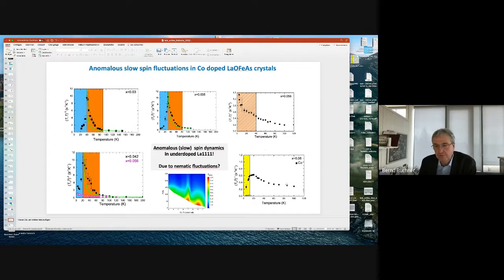Even if you go to the best superconductor, you still have this increase of the relaxation rate, telling you you have a very unusual slowing down of magnetic fluctuations. So magnetism is highly anomalous here in this sense. And of course, the natural way to explain this is, okay, we have these nematic fluctuations here in this region, and we have the strong coupling to magnetism as signaled here, and this means that we also have highly anomalous spin fluctuations. So you could also argue, yes, superconductivity is occurring close to nematic order. However, we know that also spins really are anomalous in this region, and this could also be very relevant.